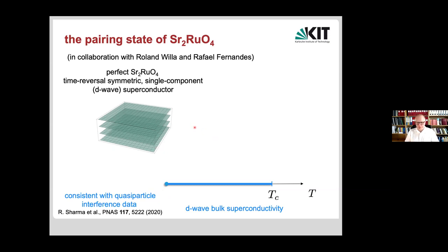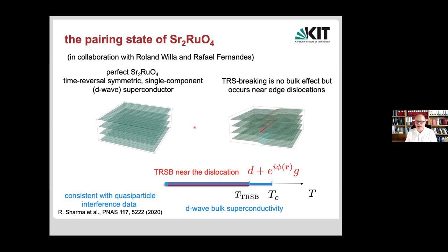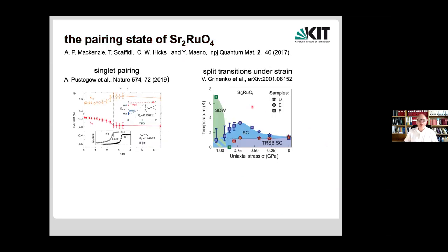And of course, you might ask, what about the time reversal symmetry breaking? And the statement that we are making is that the time reversal symmetry breaking may well not be a bulk effect in the system, and I will discuss this in some detail. But in fact, it is something where the system has local edge dislocations, and that you find a separate phase transition near edge dislocation that breaks the time reversal symmetry in the system. So let's go a little bit over the data that we have to motivate this.